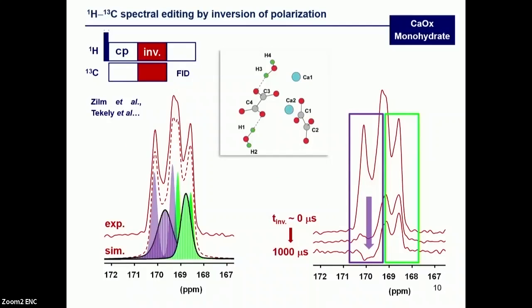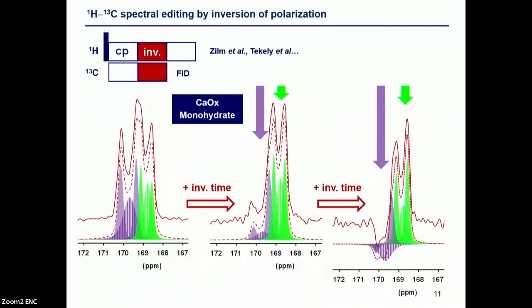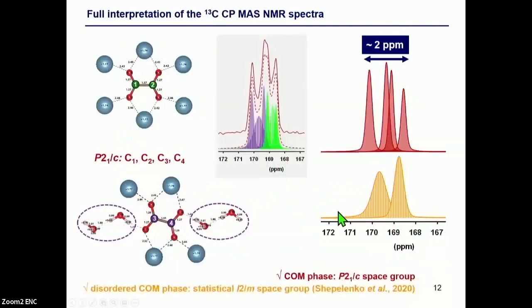And we could make it a little bit more quantitative by simulating all the spectra by increasing the inversion time. And you see, the conclusion is exactly the same. You have always this inversion of the most shielded part of the spectrum included, and that's very important, included the broad component, which is represented here and which is here negative for this particular inversion time.